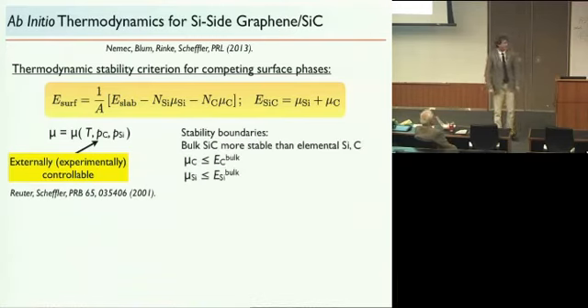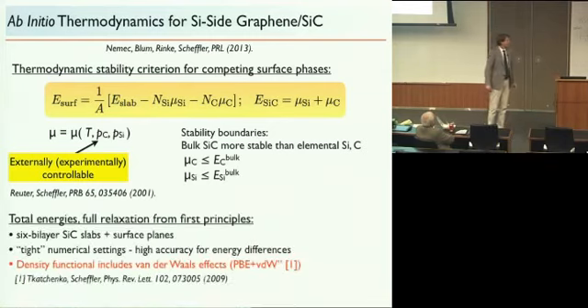Now, there are some stability boundaries that we can state, which is that if the carbon chemical potential was less than the energy of a carbon bulk, you could basically generate energy by destroying your system, and similarly for silicon. So you don't want to do this. This gives you boundaries, and within that, you can calculate the surface energies of these phases to investigate stability.